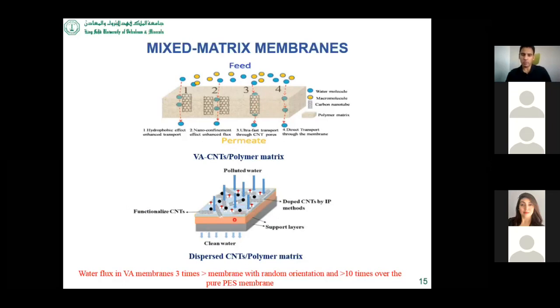So generally, the flux in this type of membrane will be 3 times higher than this type of membrane. But if we talk about the pure polymeric membrane without the modification, then of course the flux in both these cases is extremely higher than the pure membrane. And what is the significance of this? If the flux is high, then of course you can clean more water in a shorter time. Of course, you also need to focus on the removal efficiency as well. I will talk about that in the coming slide.